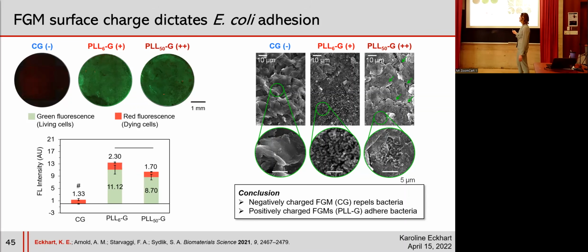And then with the PLLG, we see numerous bacterial cells on the surface of the pellet, and they're mostly living, which is consistent with our hypothesis that a positively charged material would adhere negatively charged bacteria. And this result was confirmed using scanning electron microscopy. We can see the bacteria cell walls appear to be intact. They appear to be happy living on that surface.